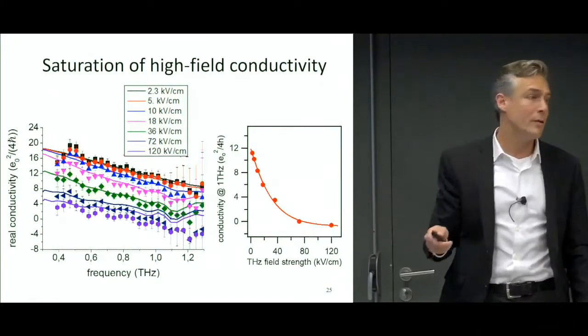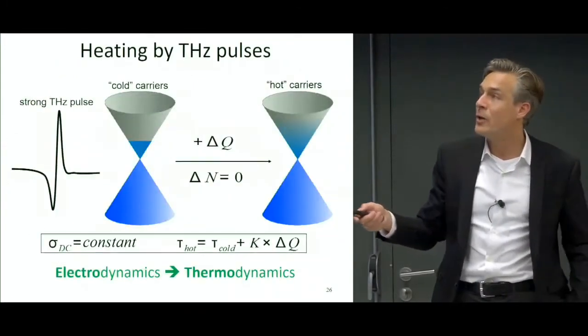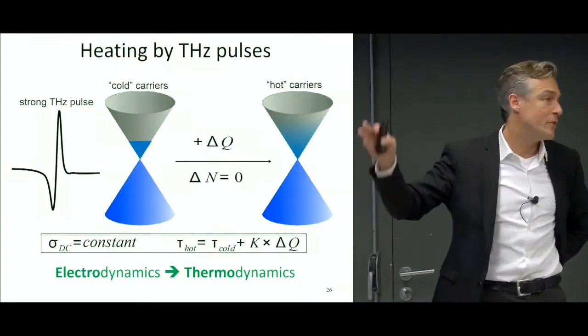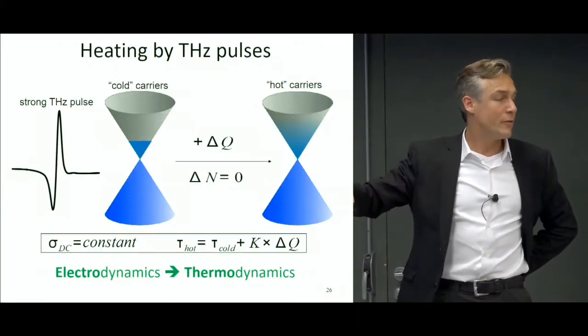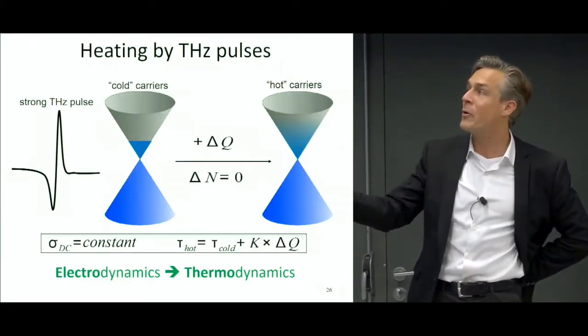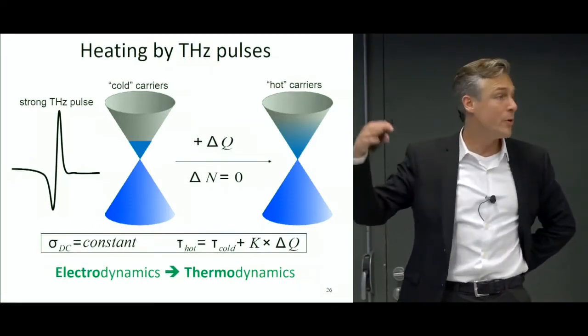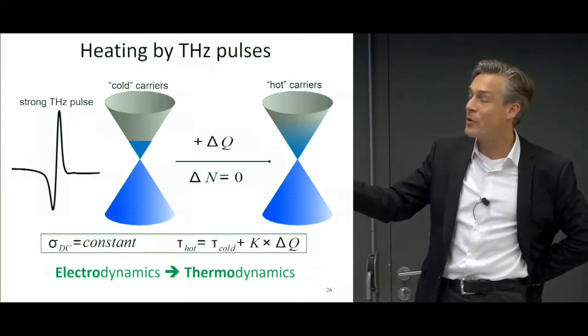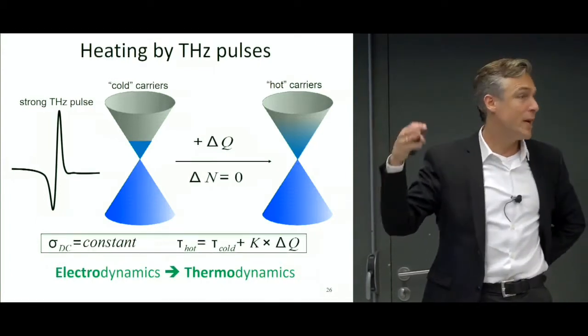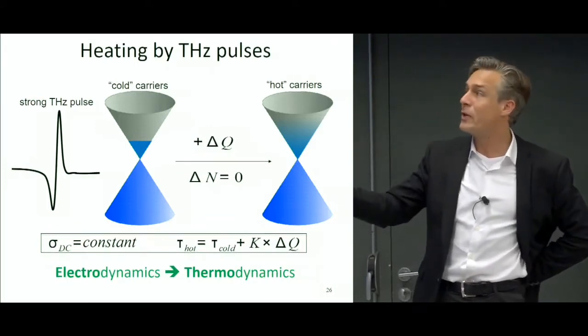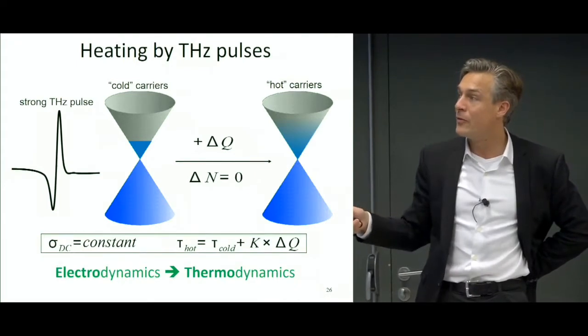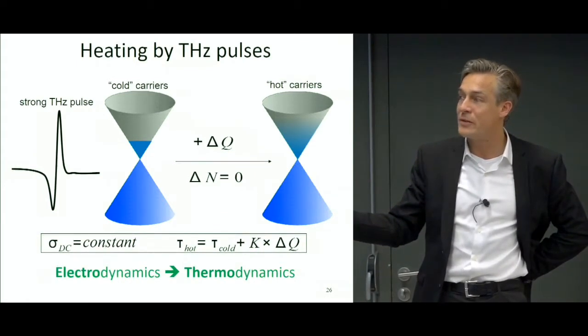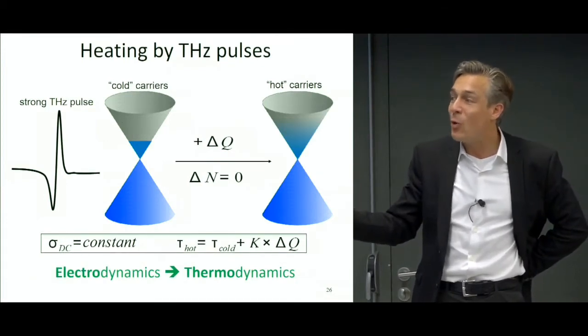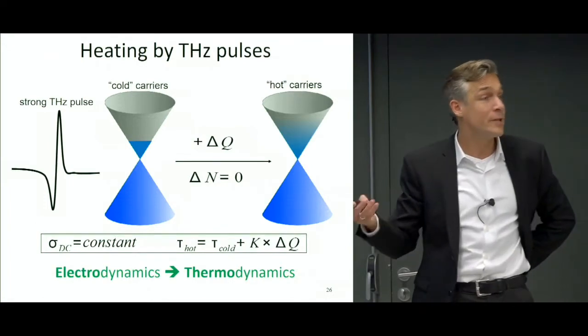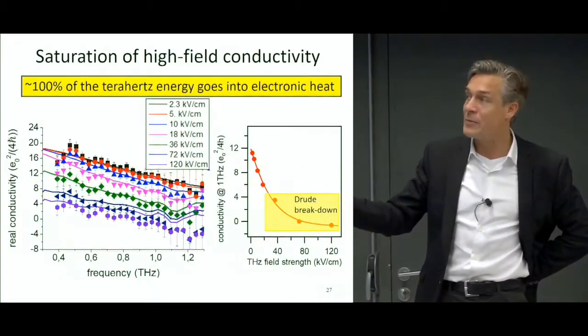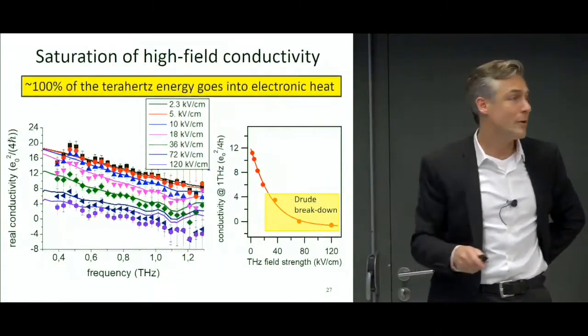The lines that you see here are a very simple model that we implemented, where we said, okay, this terahertz pulse has an energy of about a microjoule. We know that the graphene absorbs about 5% of that pulse, so we know how much heat goes into the electronic heat system. We know the heat capacity of the electronic heat system, so we know the temperature of the system. We're not changing the carrier density, we're not injecting carriers, we're simply heating up the electron bath, and so you can describe all the electrodynamics simply by thermodynamics. It's really quite a simple model, and that describes the data very well up to very high field strength.